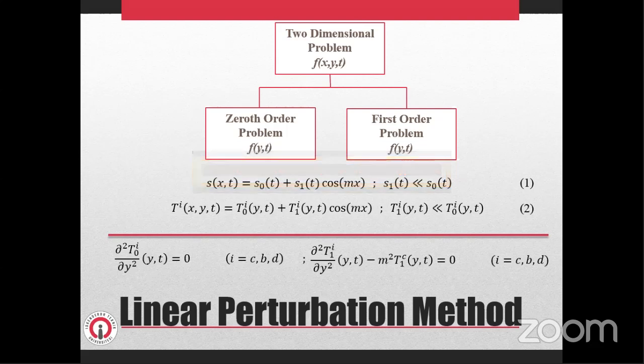For this reason, the temperature fields are expanded in the vicinity of the mean shell thickness for y equal to S0t in the form of a Taylor series, since the perturbation on the shell thickness S1t is very small compared with S0t. Then the boundary conditions can be written by separating periodic and uniform terms and dropping the second and higher order and product terms in the small quantities.